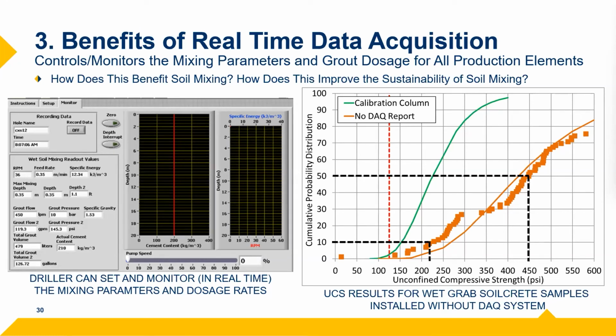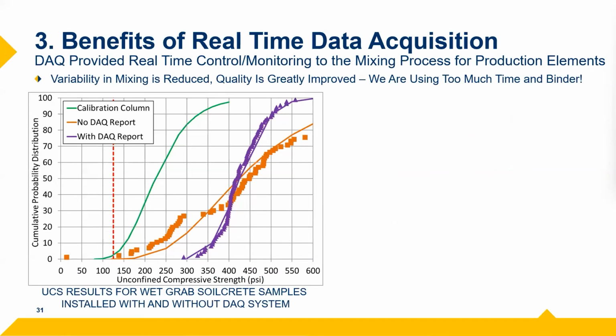And so we said, okay, we're going to try to calibrate ourselves, do a little bit better. We had our data acquisition system in there, and then we start measuring this purple data. What we notice right off the bat is that we've reduced the variability in mixing. The quality is greatly improved. Our average value is about the same, right? We're still in that 400 to 450 PSI. But where we see the huge difference is at this 10%, at this 90% passing value.